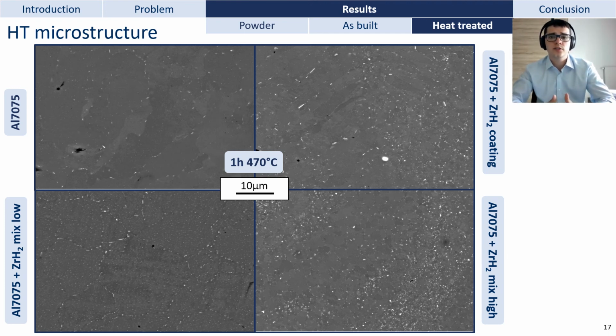This treatment is composed of two phases: the solution heat treatment, which is 1 hour at 470 degrees to solutionalize the uncontrolled precipitates of the as-built microstructure, and the aging heat treatment, which consists of 24 hours at 120 degrees, and that will control the growth of the precipitates to obtain the desirable hardening eta prime precipitates.